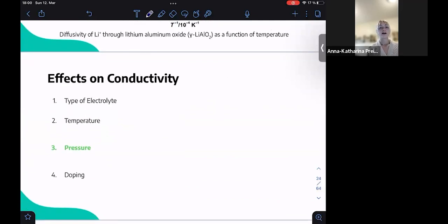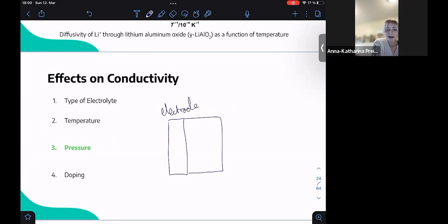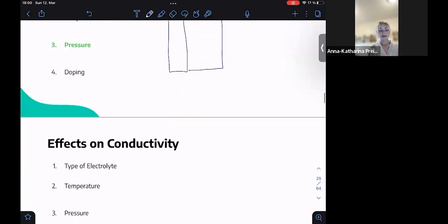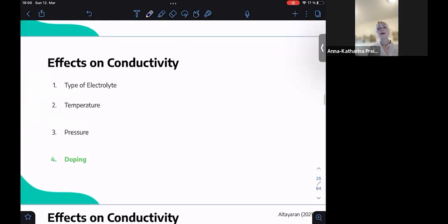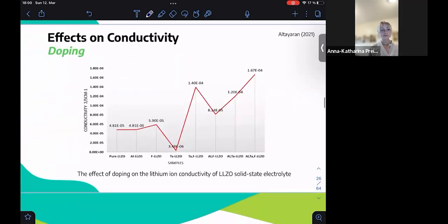Next, pressure. If we apply pressure, it increases the contact area between the electrode and the solid electrolyte, and this basically promotes ion transport. However, high pressure can also lead to mechanical failure and reduce the durability of the electrolyte. And then lastly, we have doping. By introducing dopants or impurities into the solid electrolyte, it can alter its ionic conductivity by modifying the crystal structure, electronic properties, or defect concentration.